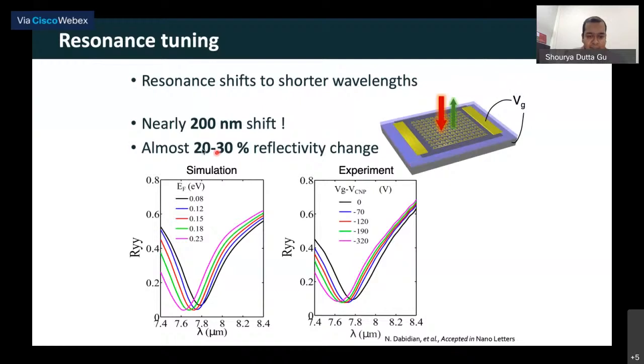Now, this is the simulation. The horizontal axis is the wavelength of light that we are sending in. The vertical axis is the reflectivity. As I increase the Fermi level from 0.08 electron volts to around 0.23 electron volts, I see that the resonance wavelength, shown by this dip, which is around 7.8 microns at 0.08 eV, moves to around 7.6 microns, shown in the purple curve.